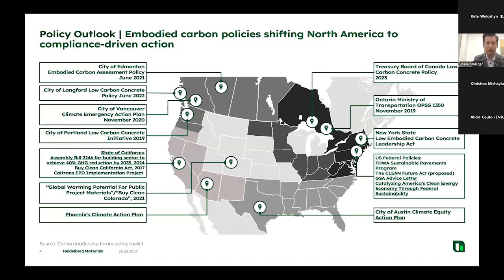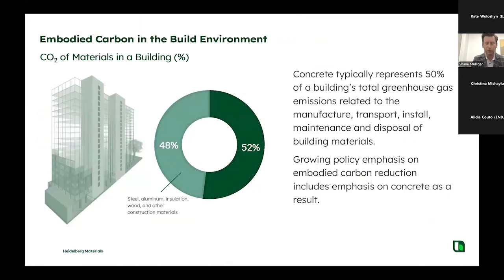And when we're talking about embodied carbon, we're generally talking about concrete. Because concrete, as you know, is one of the largest embodied carbon contributors to most types of infrastructures. When we're talking concrete in the built environment and particularly vertical construction, we find that 50% is generally the ballpark of where concrete is contributing to the overall carbon footprint of a building. Sometimes it's a little bit less, like in a residential single-family home, but it could even be more if you're looking at a very tall high-rise building that has a very deep parkade structure.